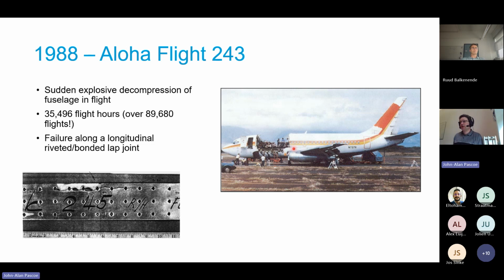Of course, this was investigated to understand what happened, and it was found that this was a very heavily used aircraft, with 35,000 flight hours, but over almost 90,000 flights, because it was used for flying between islands in Hawaii, so very short flights, lots of flights in a short amount of time. In a very corrosive environment, right? Warm, humid, salty. And it was found that there was a failure of a longitudinal riveted and bonded lap joint. So along this fuselage barrel, it's made of overlapping panels. And at one of those joints where the panels overlapped, they found a collection of cracks joining together all these rivet holes and just unzipping the whole joint.